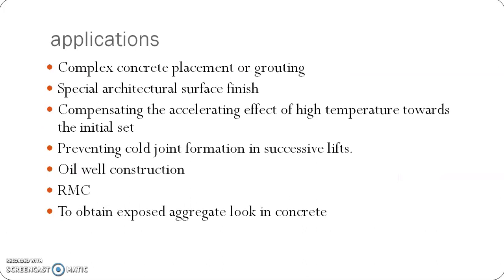So what are all the applications of retarders? Retarders are used in casting and consolidating large pours without the formation of cold joints. That's why they are used in grouting of oil wells. Oil wells are sometimes taken up to a depth of about 6,000 meters, where the temperature is around 200 degrees Celsius. The annular spacing between the steel tube and the wall of the well can be sealed by means of cement grouting. In that case, for grouting, we can use retarders.